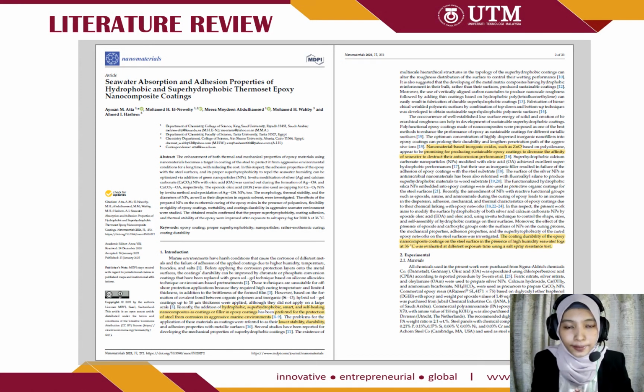As for the research in this nanocoating area, it has received increased attention from all over the world. A research by Ayman Atta et al. has captured my attention on seawater absorption and adhesion properties. This research stated that epoxy coating has been preferred for the protection of steel from corrosion in seawater. And nanomaterials based on inorganic oxides, that is zinc oxide, appear to be promising for producing sustainable epoxy coating to decrease the affinity of seawater to disrupt the anti-corrosion performance.